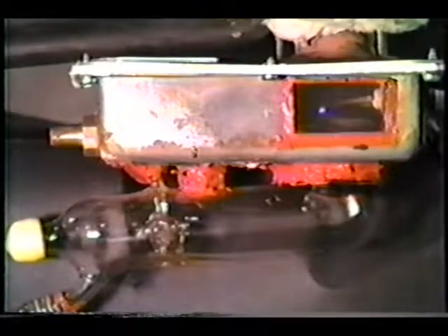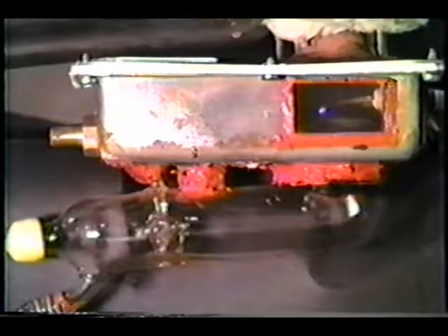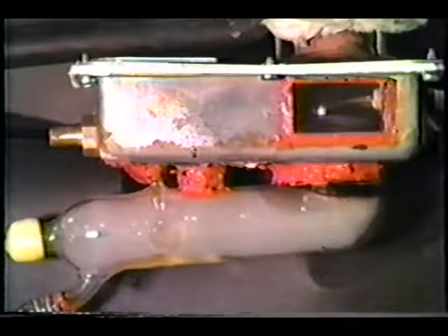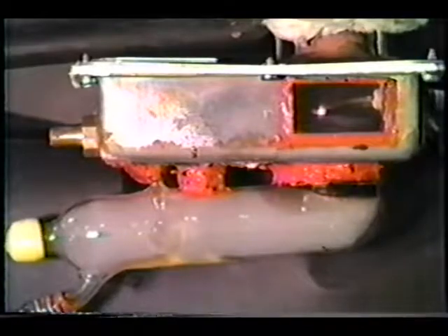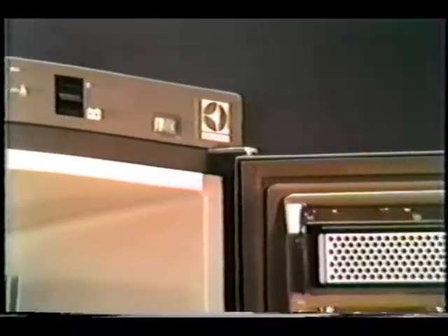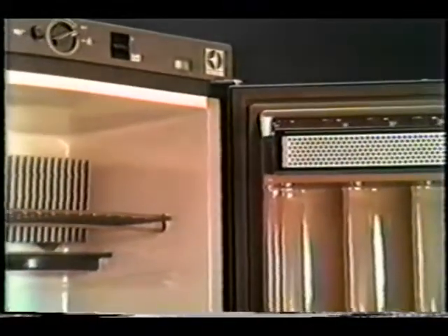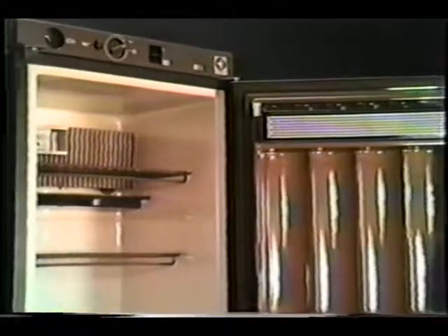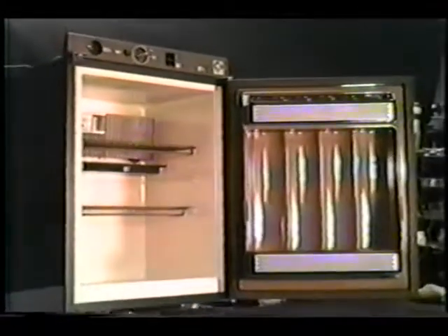After several basic experiments, a commercially available absorption-type refrigerator was fitted with a Babington burner containing an impactor. This glass prototype was sized to produce 400 BTUs per hour to match the heat output from the propane burner that normally powers the refrigerator. No other modifications were necessary. This new diesel-fired refrigerator has operated successfully for extended periods without signs of coking or carbon formation.